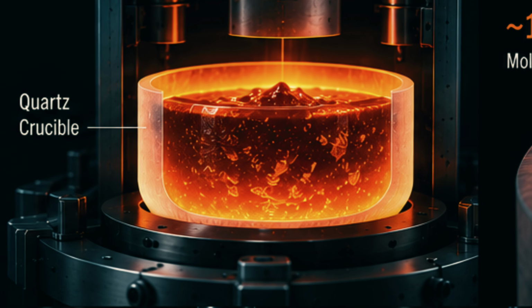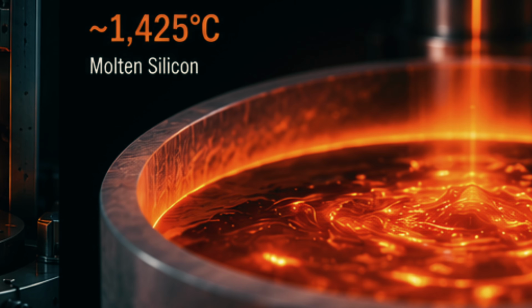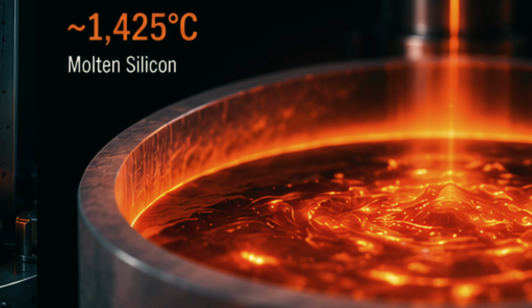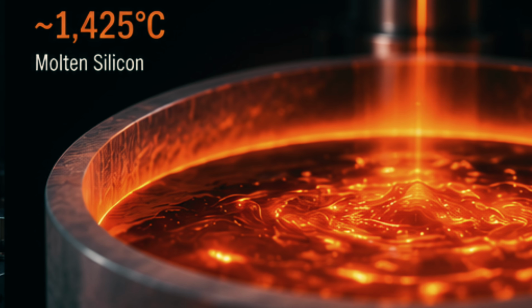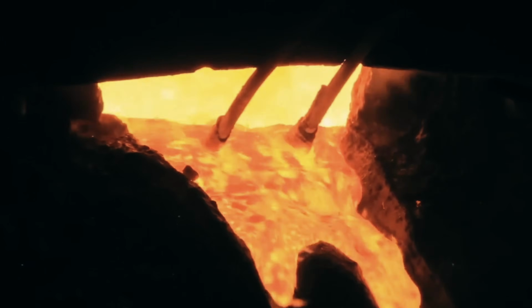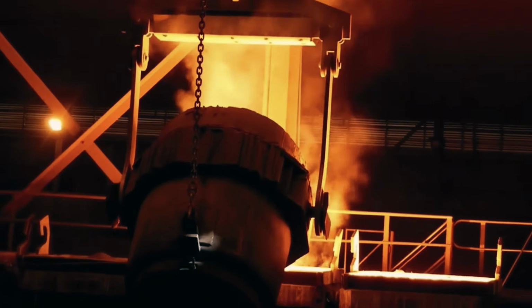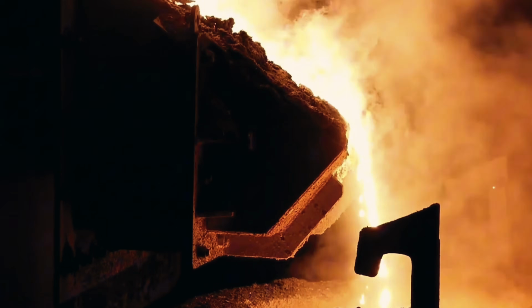Chunks of the polysilicon are melted down in a quartz crucible at around 1,425 degrees Celsius, just above silicon's melting point, held with almost no margin for error. A few degrees off in either direction and the whole batch can fail.